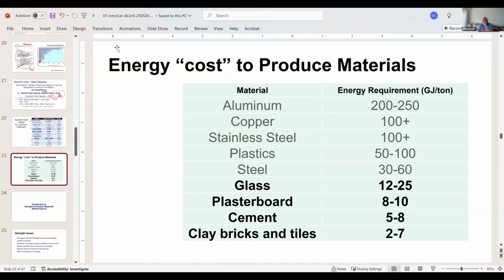Several years ago, I was working with Boston Valley Terracotta, and they were getting a lot of pushback on the amount of energy necessary to produce terracotta. And it comes from architects and what have you. Well, it's not a very environmentally friendly material. Turns out it's a very environmentally friendly material in terms of amount of energy per ton. Terracotta falls into this clay, brick, and tile range. It is the lowest energy requirement for any of the materials produced. Cement is surprisingly low here, and glass is our most expensive.